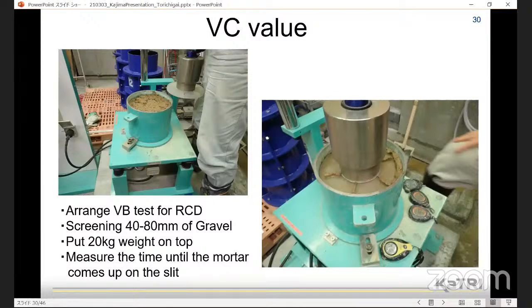This slide shows the VC test, a method for evaluating the fresh property of RCD concrete. This test is an arrangement of the VB test for RCD. Coarse aggregate of 40 millimeters or more is screened, and with a 20 kilogram weight on the top, vibrate the lower shaking table and measure the time it takes for the mortar to come up on this slit.